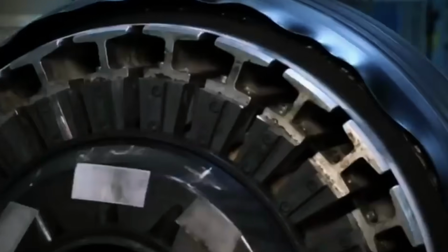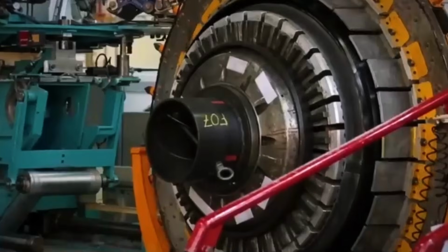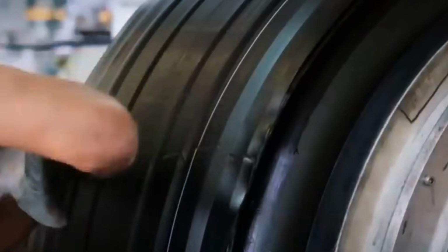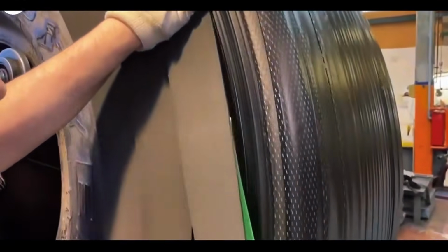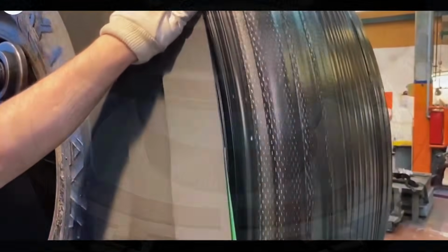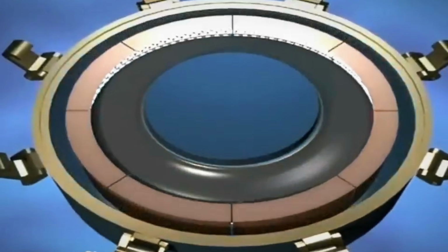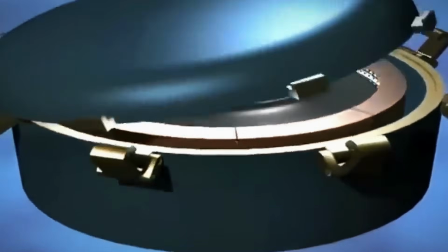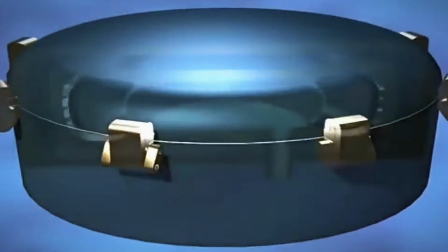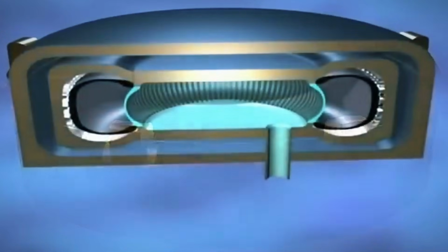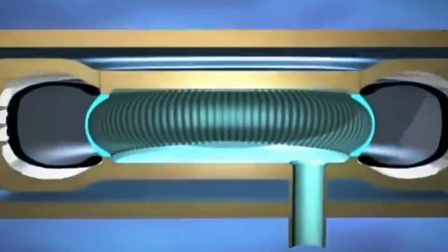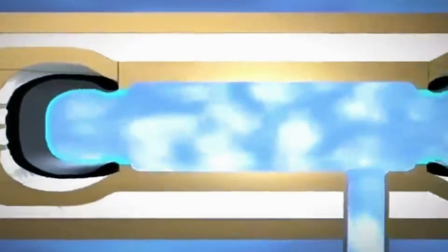All components converge at the tire building machine, the central workstation of the factory floor. The machine operates around an expandable metal drum. Unlike high-speed automated car tire lines, this machine works at a deliberate, controlled pace, every layer verified before the next begins. First, the inner liner is applied to the drum, a completely airtight rubber layer that will hold over 200 pounds per square inch of pressurized nitrogen without allowing a single molecule to escape.